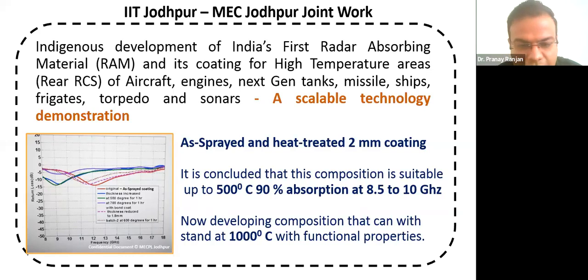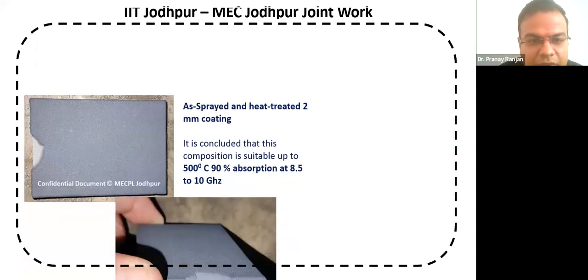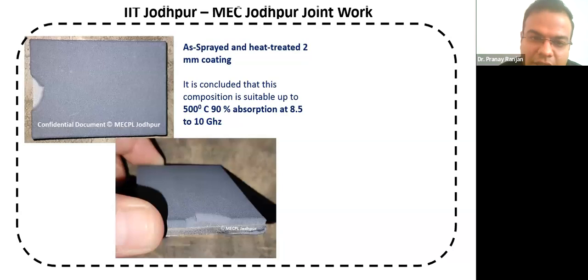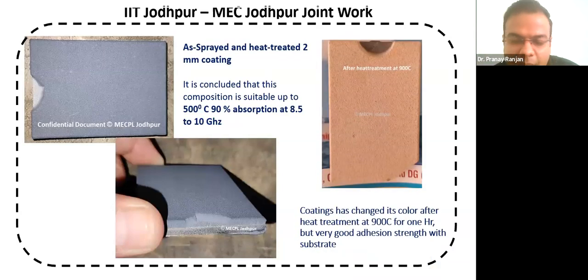So till 500 degrees Celsius, we have demonstrated and got certified from a defense lab, and we are trying to develop till 900. But at 900 degrees Celsius, which is the ending point of the fighter jets' high temperature, we found that our material is changing color. So at present we are working on this. However, still at 900 degrees Celsius, our material is in good shape. It does not lose strength, but the changing color is a concern for us, and we are working on it.